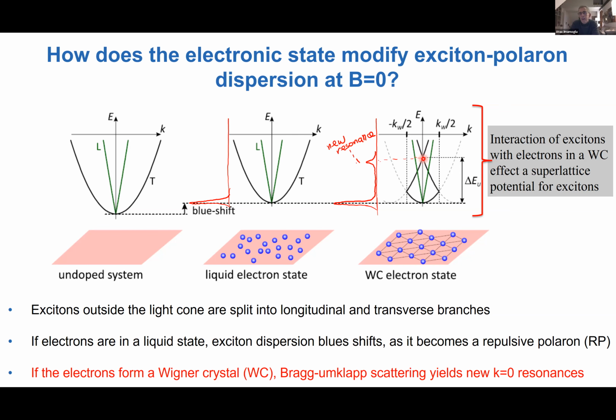of new resonances and the reduced Brillouin zone at the zero superlattice potential, I should say. And these umklapp resonances hybridize with the k equals 0 and pick up an oscillator strength. And therefore, they will become visible in resonant absorption, even though they originate from high momentum excitons with the momentum that corresponds to a wavelength that is equal to the lattice constant, which, as I said, is on the order of 20 nanometers. Okay, so this is the essence of our measurements that I will show you,